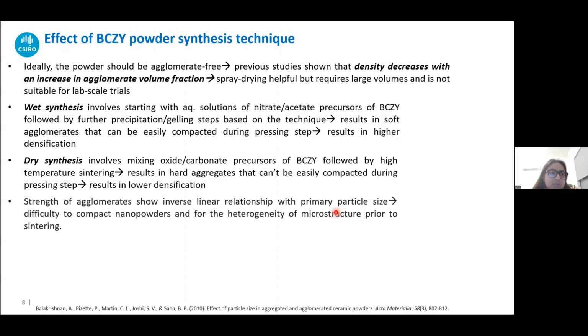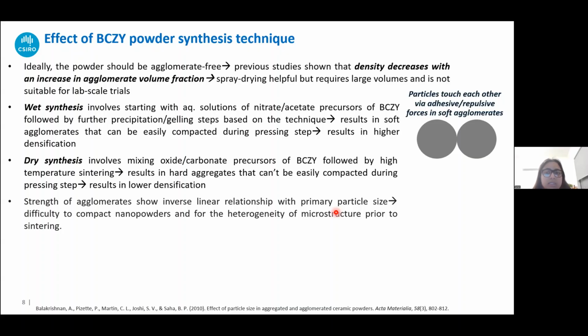So mainly there are two synthesis techniques, as I already mentioned. Now in the wet synthesis technique, the agglomerates that are formed are soft agglomerates. So these are particles that are just touching each other via adhesive and repulsive forces. These agglomerates can be easily broken down when the material is pressed, like with isostatic pressing or uniaxial pressing. When the material is compressed, the agglomerates get broken down. So this results in higher densification during the sintering step.